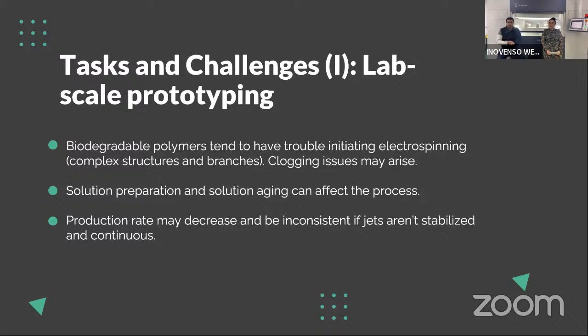Another issue is the solution preparation. There are certain cases where you can use a solvent and dissolve the polymer, but you may not necessarily be able to upscale it. It might be too dangerous. You need to worry about the solvent you're using, because when you transition to the industrial scale, you're going to use quantifiably larger amounts of solution, and it's dangerous if your solvent is volatile, especially if it has a very low flash point. So we wouldn't recommend using solvents with very low flash points, especially at industrial scale, because there's a chance of fire hazards. So that's one issue.